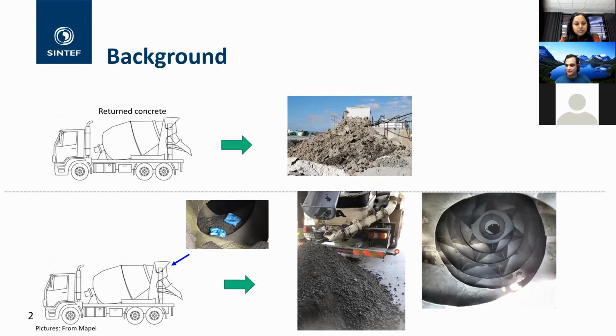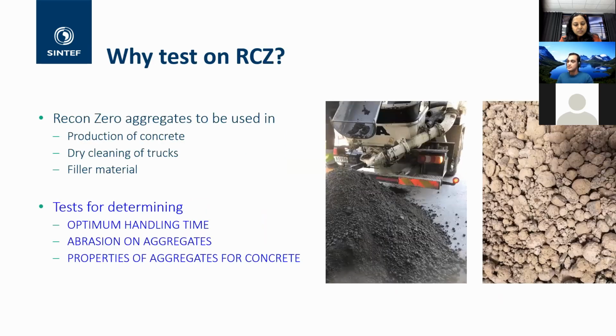And in my test, I washed the concrete drum for multiple cycles, as these aggregates can be used for multiple cycles without adding more Recon-Zero powder. So, why did we need to test the Recon-Zero aggregates? And now I'm using the term Recon-Zero aggregates for the aggregates produced by using Recon-Zero powder, because as I already mentioned, we wanted to use them back in production. And we wanted to know what is the optimum handling time of these aggregates, or to rephrase, after how many days can we use these back either in production or for dry washing of these concrete trucks.